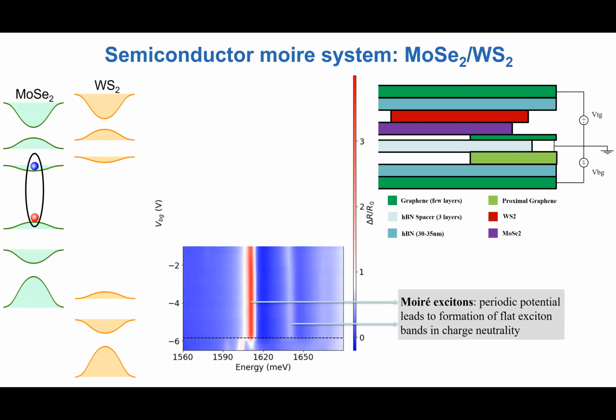So now again, I do the same trick. I first show you the regime when the chemical potential is in the gap. Now, the main difference is that instead of having just one exciton resonance, I have several. And this is due to the fact that the excitons now see an effective center of mass potential. Because the conduction and valence band potentials are different, the exciton that forms out of the electron hole pair is subject to a potential, and that results in new excitonic bands.